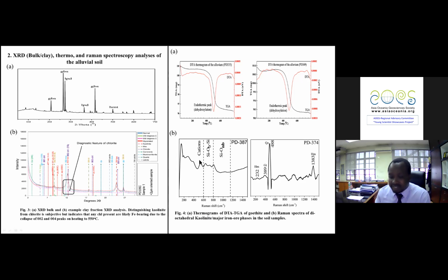The Raman spectrum of the octahedral kaolinite is divided into 3 regions. As you can see, the peaks that occur within the frequency range below 600 are from a set of complex cation translation motions that link to interlayer site and octahedral sites relative to silicate groups in oxygen hydroxides and interlayers.